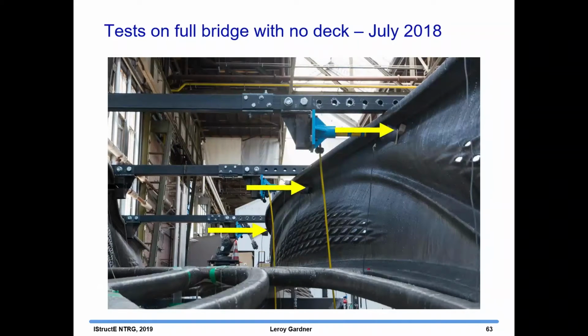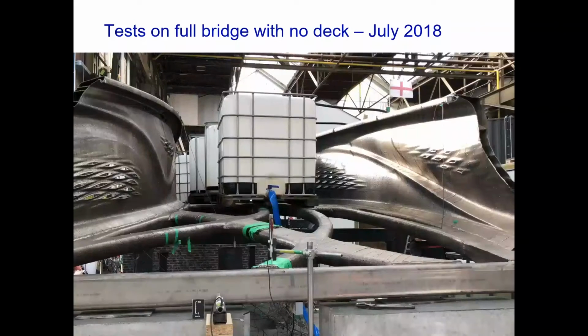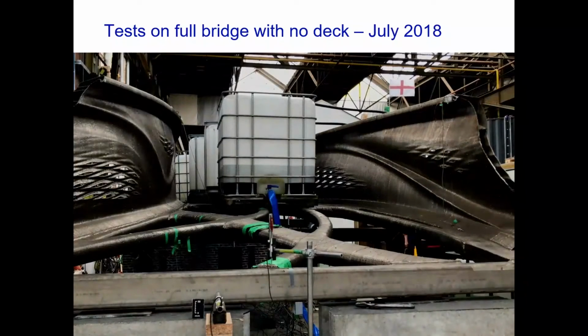So we carried out both horizontal loading on the handrails to simulate pedestrians pushing on the handrails, and also vertical loading. So vertical loading was initially achieved through water tanks. So we had a series of water tanks, 1 meter cubed, so 1 ton of loading per tank, and we loaded them up as evenly as possible.